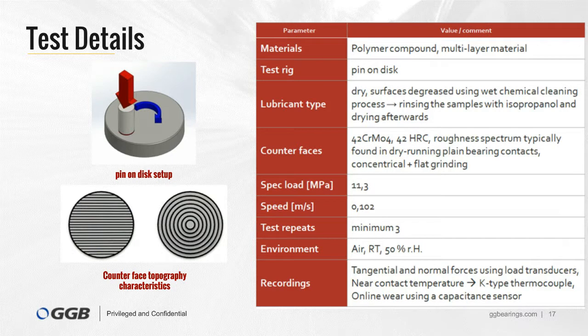We used a flat-on-flat test configuration, realized through a pin-on-disk setup. The image on the left shows a schematic illustration of such a test setup. In this test, a small test sample pin is pushed against a flat rotating disc. In our configuration, the pin is the bearing material, and the steel disc was made of hardened 42CrMo4 steel.